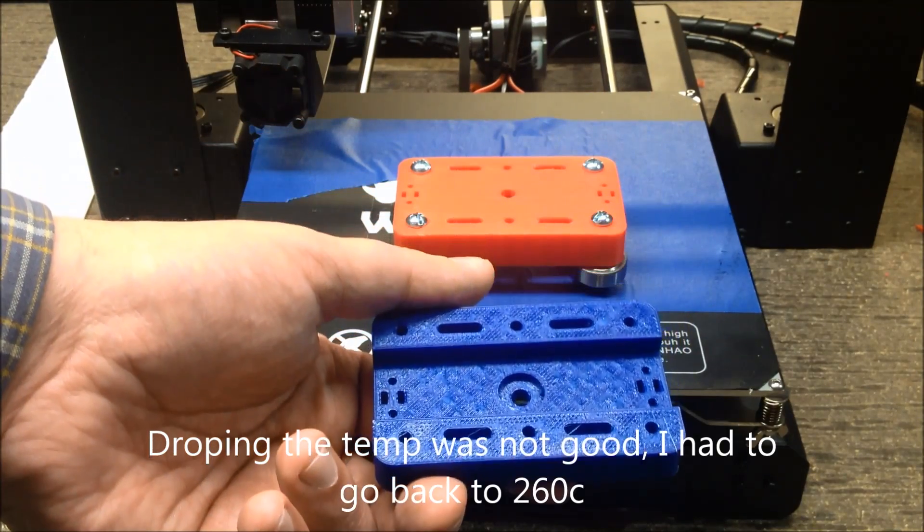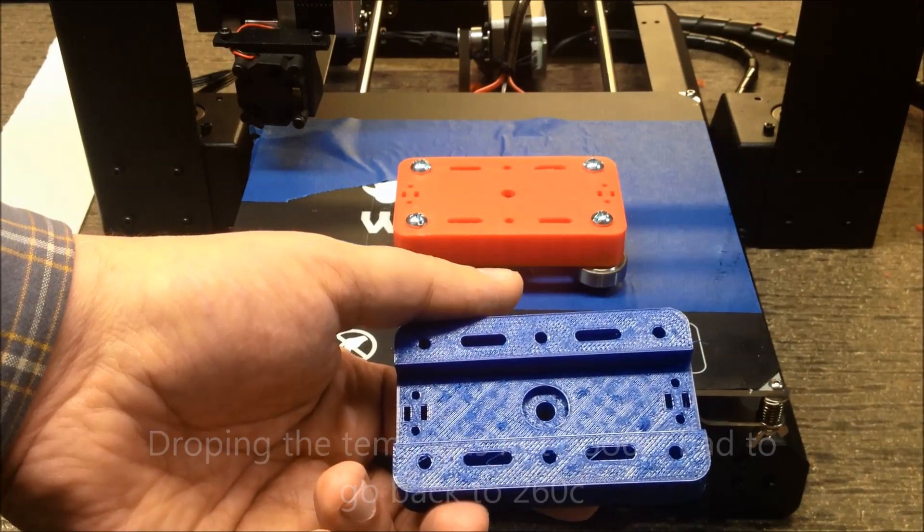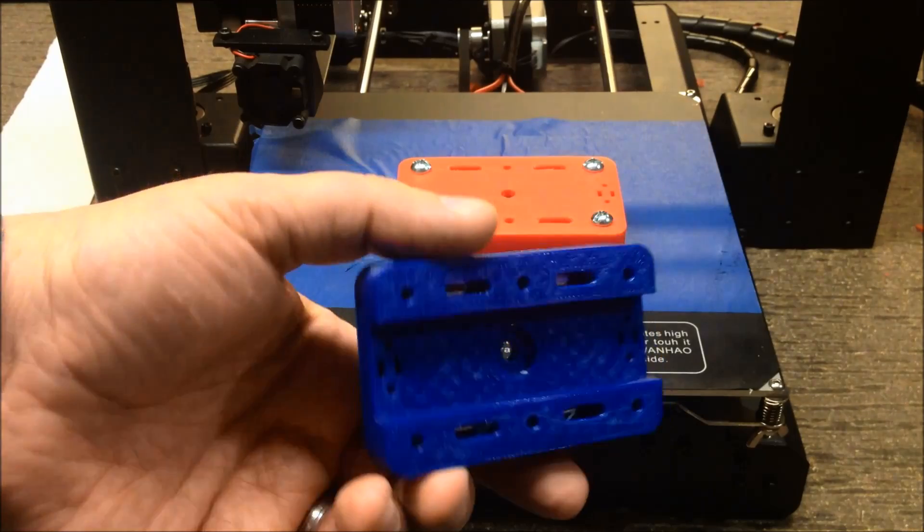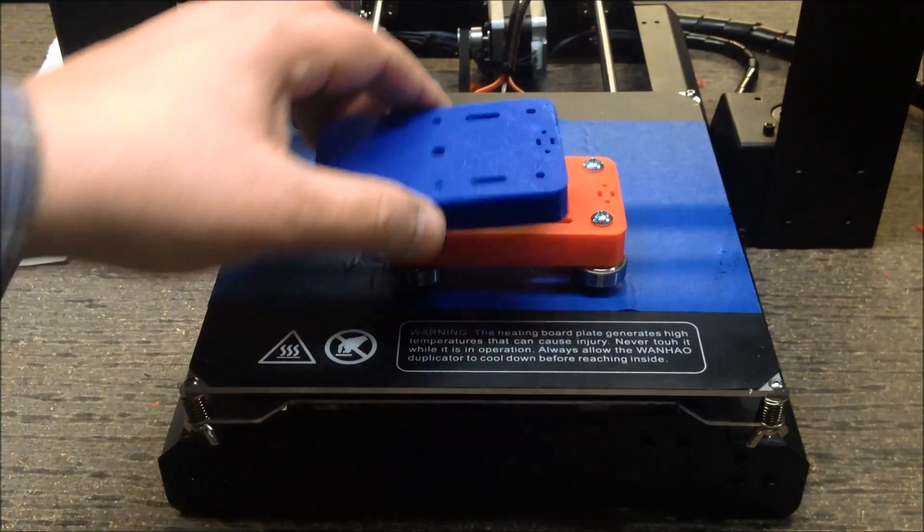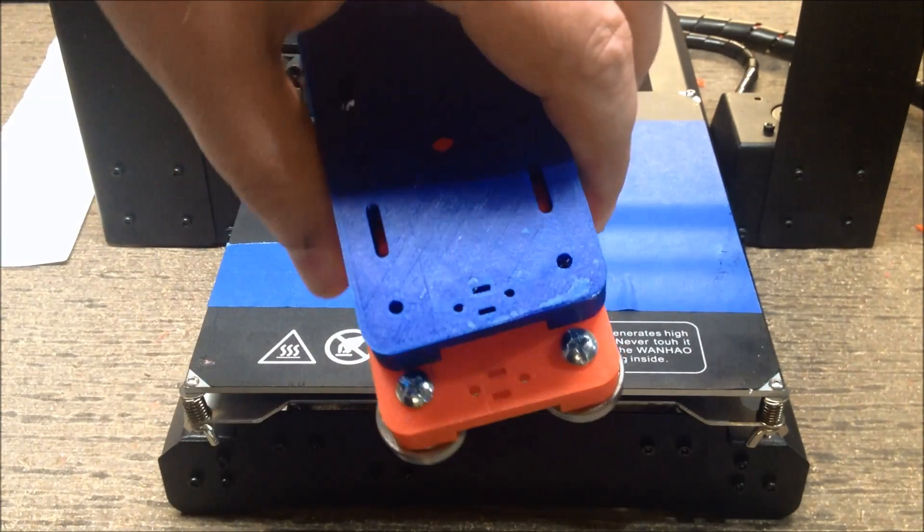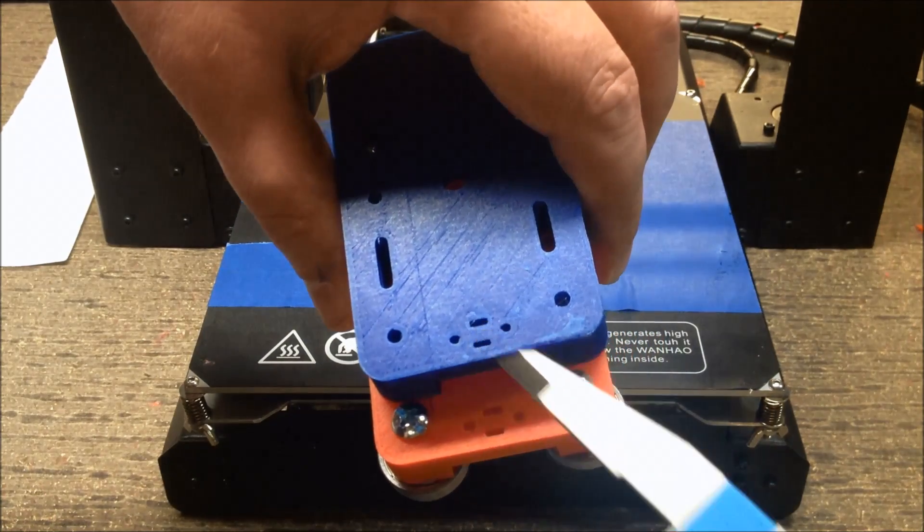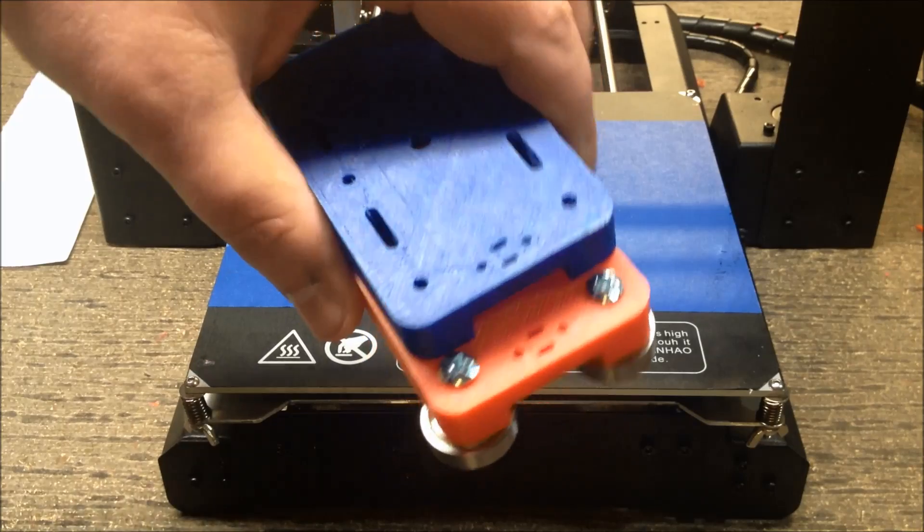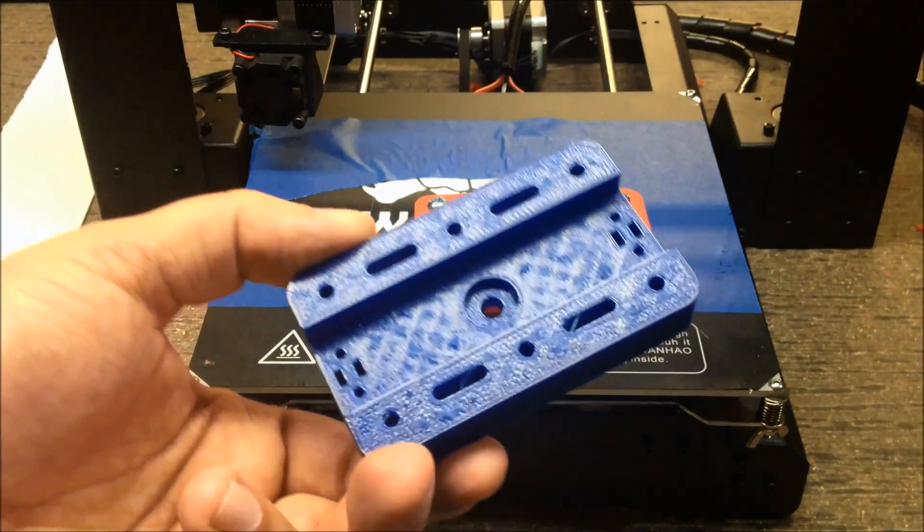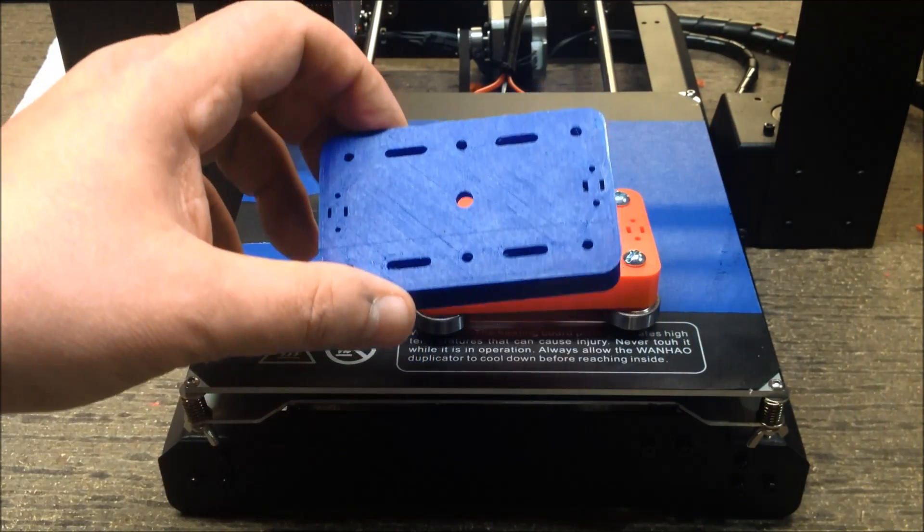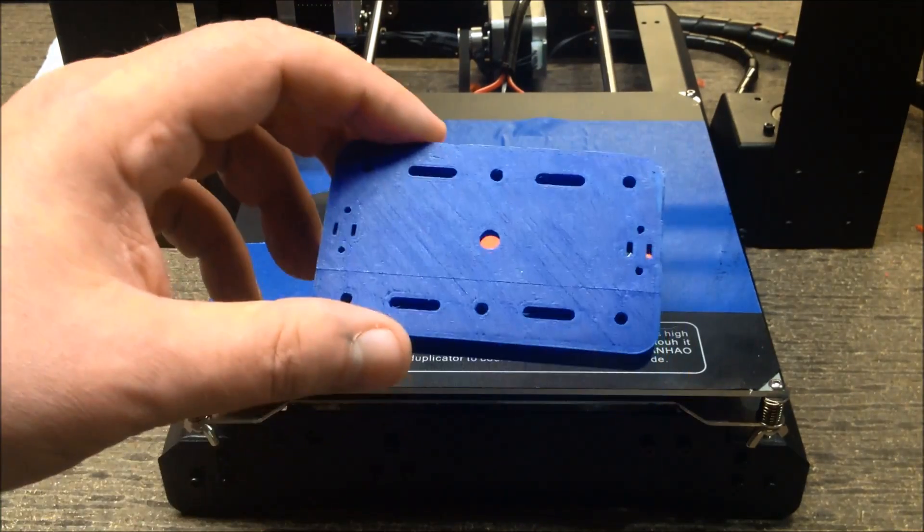I don't know if you can see some of this dithering where it filled in the honeycombs. But that could be just because I think I used two shells on this one. It's very clear from the belt holes here and here that those are definitely smaller also. If you're going to design for PETG, I definitely suggest scaling it up slightly because the sizes will be a little bit less.